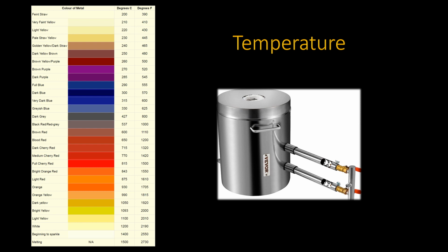The cupel must be hotter than the space around it. The extra heat comes from the oxidation reaction and other factors. Bradford in his papers state that the minimum cupellation temperature is 906 degrees centigrade, and a fellow by the name of Lodge states that for silver, along with a moderate atmospheric draft, the temperature should be between 650 and 700 degrees centigrade. More on this later.